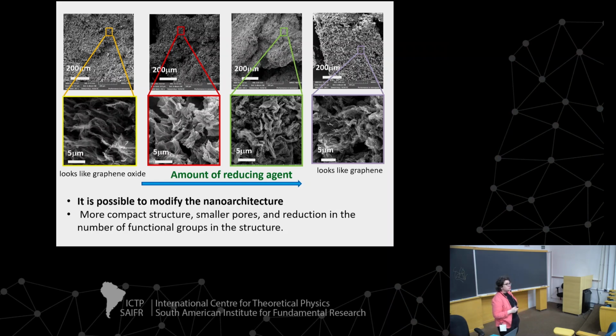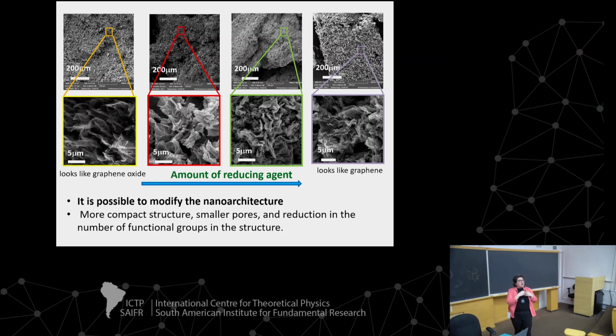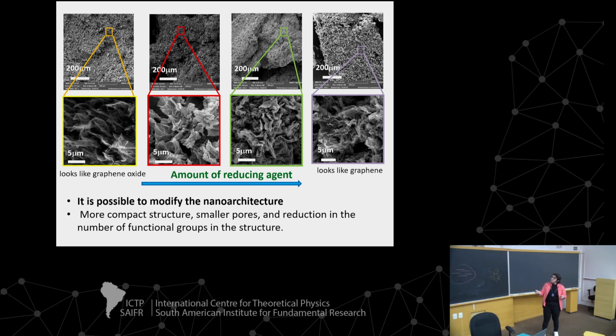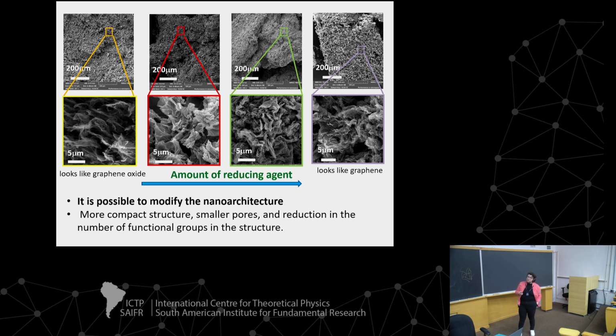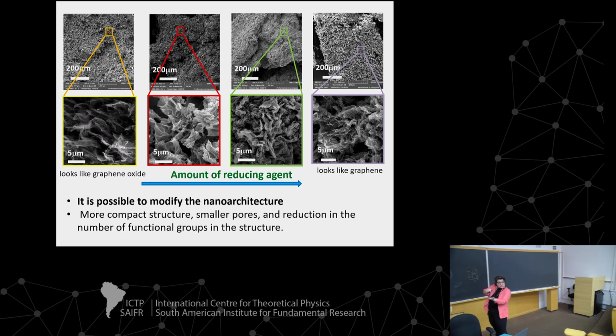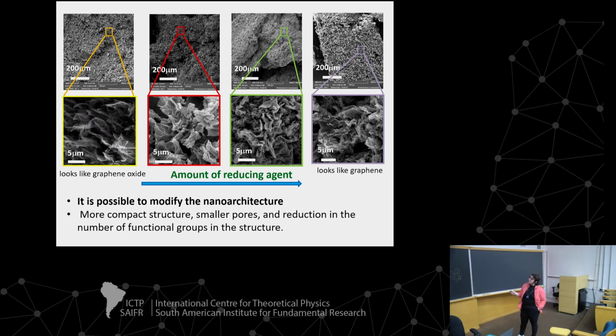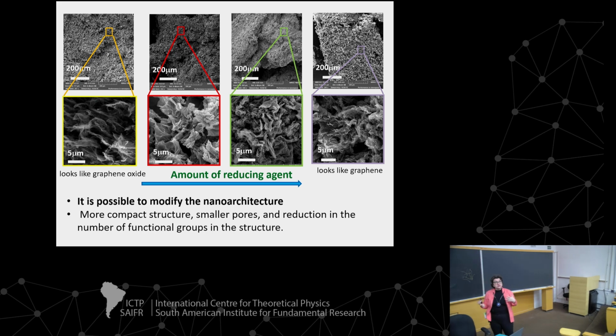With these materials, we can nano-architecture the structure only by choosing the amount of reducing agent. The reducing agent we use removes the oxygen, connects the sheets, and transforms the material. This part is less reduced, so it looks like graphene oxide. Here, we have more reducing agent, and the material looks like the graphene structure. But all the materials are very porous. We can modify the nanostructure. With more reducing agent, we have a more compact structure, so the sheets get closer, and we reduce the amount of functional oxygenated groups, and we can design the material according to the needs of the application.